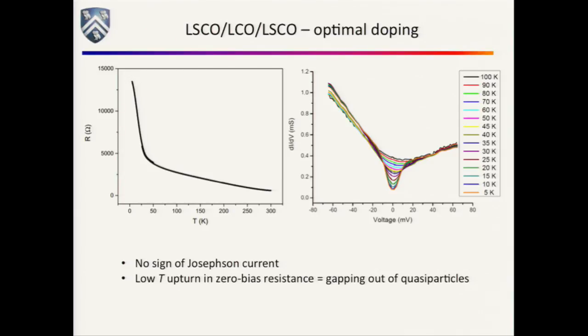So that's kind of the story there. Notice it is asymmetric. These devices really do seem to be asymmetric. The bottom LSCO layer is thicker than the top LSCO layer, and there seems to be some issue. Basically, if you've got charge flowing out of the thick side, you tend to get higher differential conductance. That just seems to be a systematic of these structures. Not entirely sure what that is.